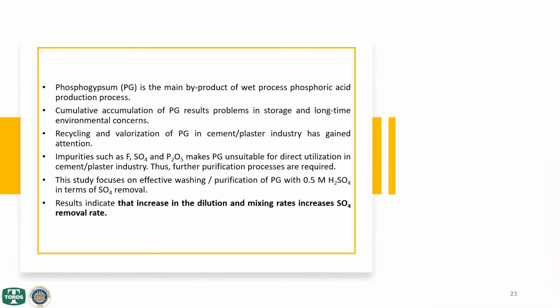So the conclusion: we can say that phosphogypsum is the main byproduct of the wet process phosphoric acid production process, and its cumulative accumulation results in environmental problems. Recycling and valorization of PG has gained a lot of attention, but its impurities make PG unsuitable for direct utilization in various kinds of industries. This study focuses on the effective washing and purification of PG with sulfuric acid in terms of sulfate removal, and results indicate that an increase in dilution and mixing rates increases sulfate removal rates.